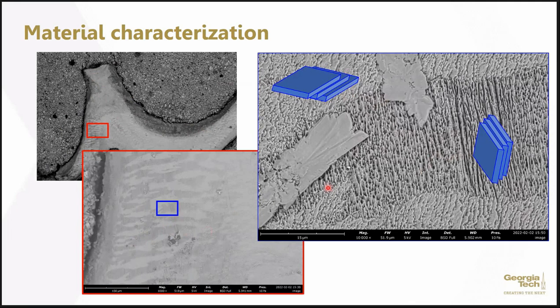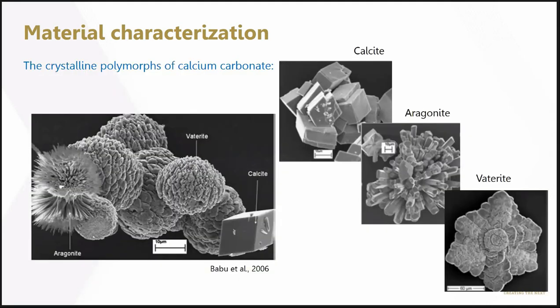We took them under XRD and EDX to look at the mineralogy and element analysis. They are abundantly calcium carbonates. The majority are calcium carbonates. Somewhere in the denticle, you may find a little bit of potassium, but not quite typical, or a little bit of silicon, but not quite typical. The majority are still calcium carbonates, but they have different forms or polymorphs of calcium carbonate.